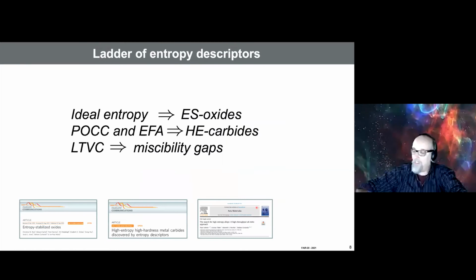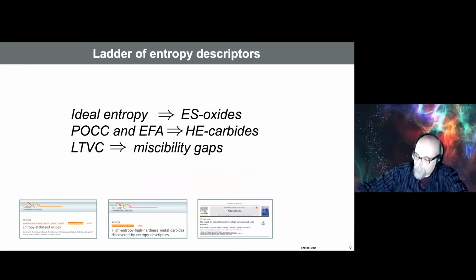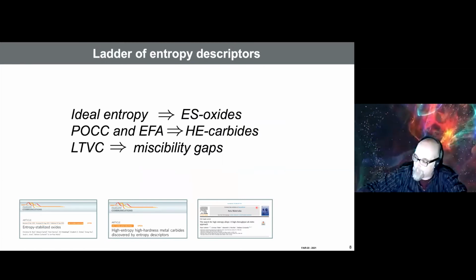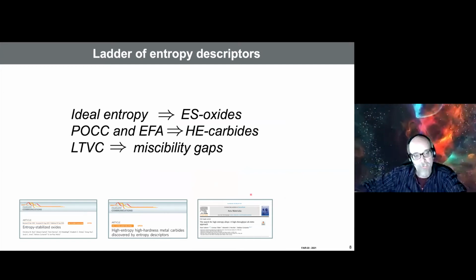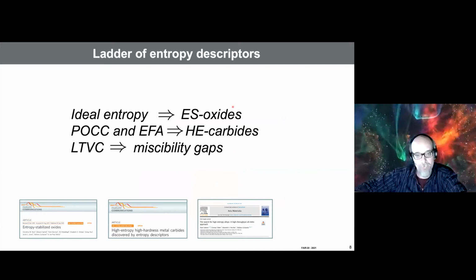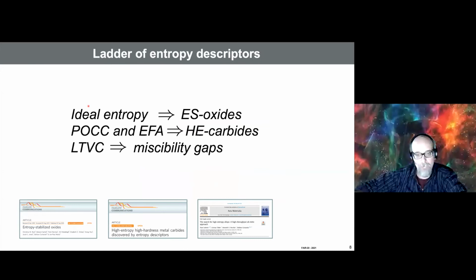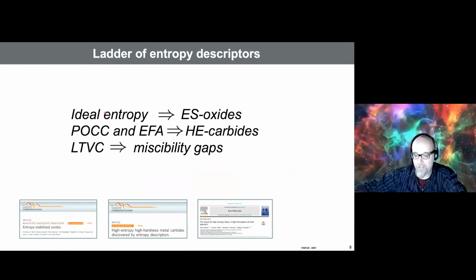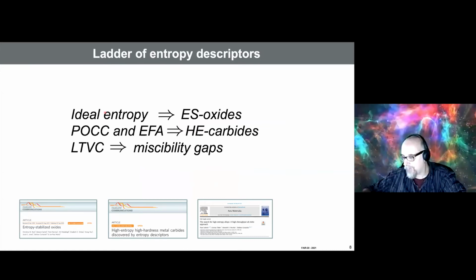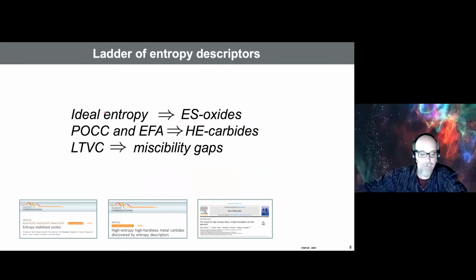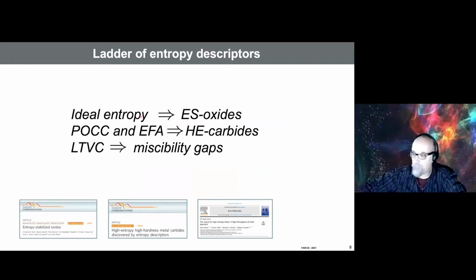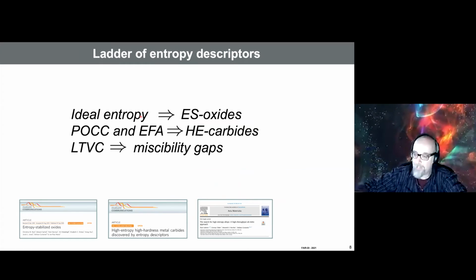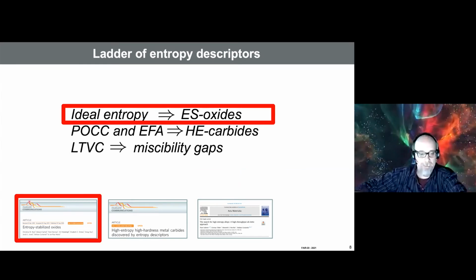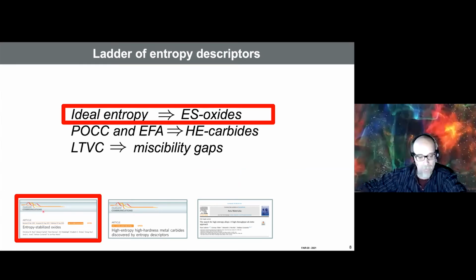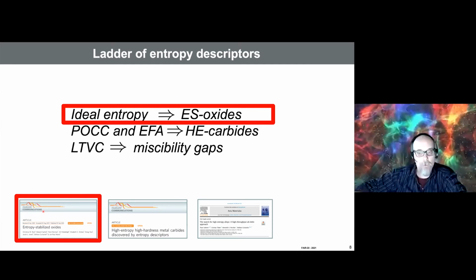So the first thing we did was to test, well, is this bogus? Is this real? Because this is really crazy. So we went on with some of our collaborators, and we tried this idea of n to n+1 phase transition, order to disorder, with oxides. Okay, and if we find something, right? And this was a completely experimental work that we did in 2015, 2016. Okay, so what did we do?